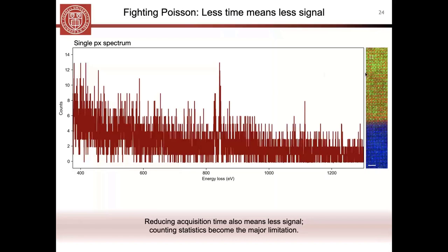And so I think for people who maybe haven't done direct detection EELS before, this is kind of surprising. And so you'll notice a few things. First of all, you notice these kind of quantized steps in the spectrum. And personally, I think this is so cool because that's really showing we're doing electron counting EELS, which I think is really kind of incredible, right? So we're really quantizing the amount of electrons that are coming into our spectrum.